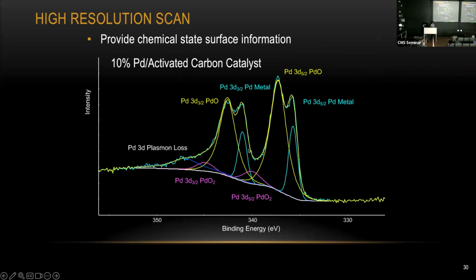Again, XPS definitely is not the best tool for this kind of measurement. It really relies on how well you can fit your peak, so you can determine different kinds of chemistry. For this sample, we see our pure palladium signal right here, but we also see some oxide with different oxidation states, PdO and PdO2. That's what people are doing when they work on any oxide and need to determine the oxidation state. You need to collect the data and do some good peak fitting.